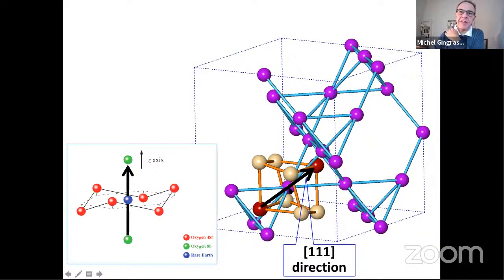So if you focus on one of the rare earth sites, what you see is that around that rare earth site there is a distorted cube of oxygen. There are two types of oxygens that surround that rare earth. Two of the oxygens reside very precisely in the center of the two tetrahedra that are connected by the rare earth site. And perpendicular to this axis that connects the two oxygens centered on these two tetrahedra is a puckered hexagon, which is illustrated on the figure here.